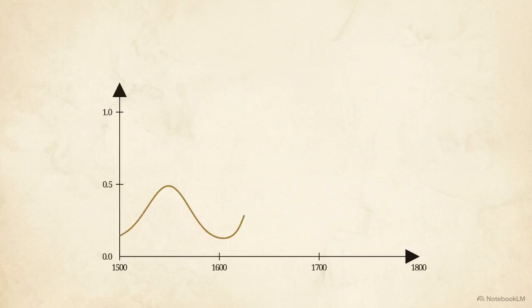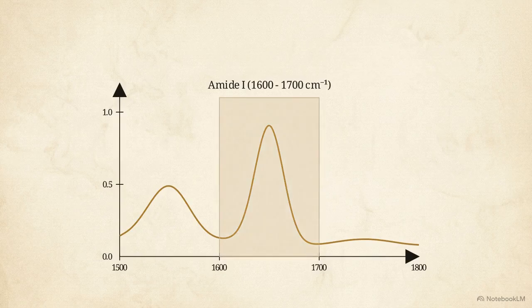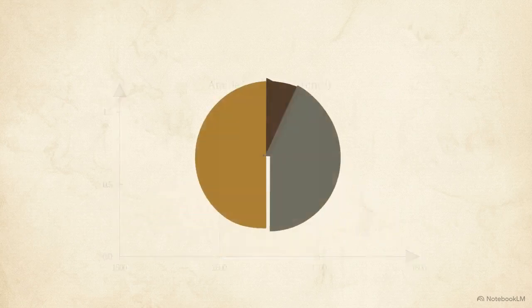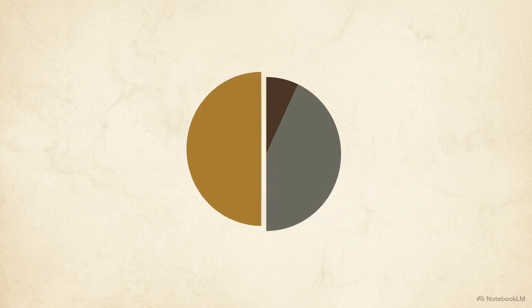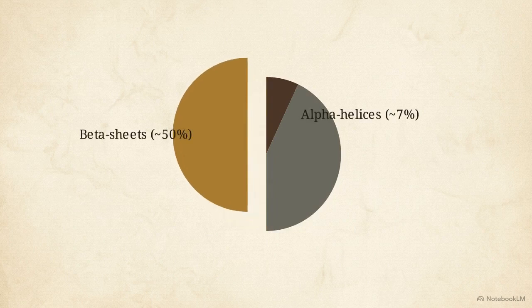Fourier Transform Infrared spectroscopy allows us to track denatured proteins in this matrix by examining the amide I region between 1600 and 1700 inverse centimeters. This specific peak identifies the presence of beta sheet structures. Deconvoluting the data reveals that beta sheets make up roughly 50% of the protein structure, far outweighing alpha helices.